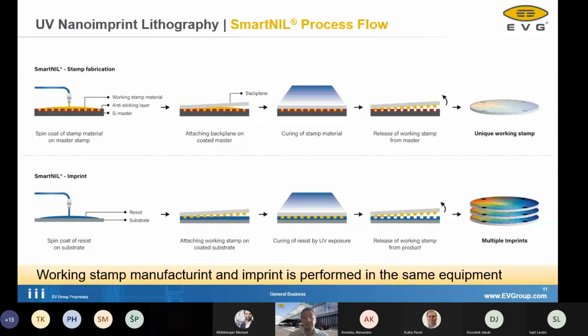And in the high volume then, when you have the structures, it's also important to be very efficient and to have good materials in place. And it's not only about just what you get on the wafer. It already starts by making the working stamp, because you need anti-sticking layers, you need special working stamp materials. Even the backplane you are using for your stamp is important to understand. Then, of course, you need an efficient curing process.